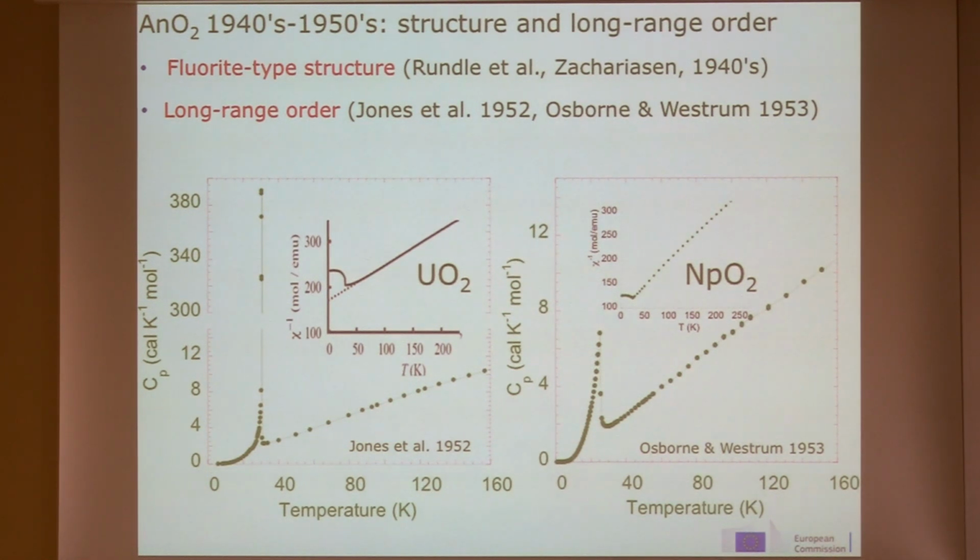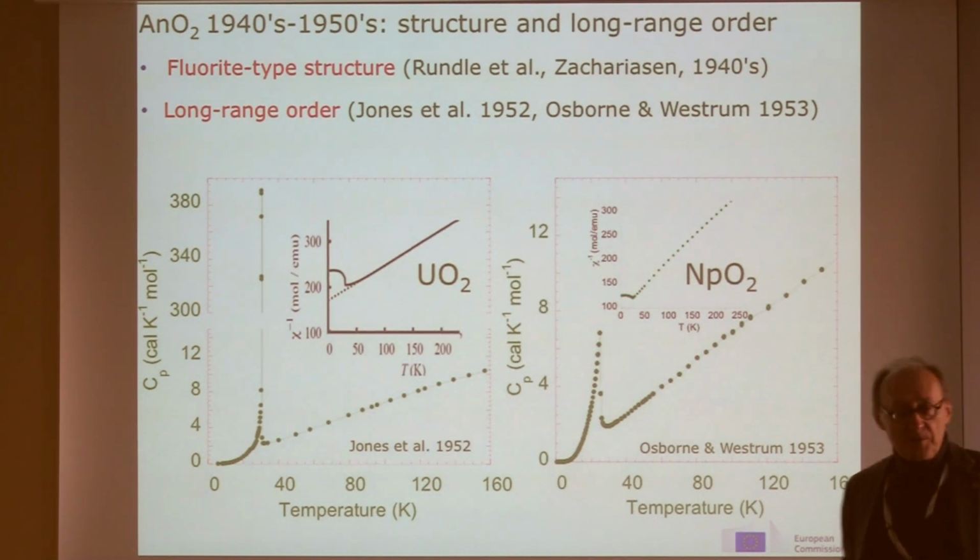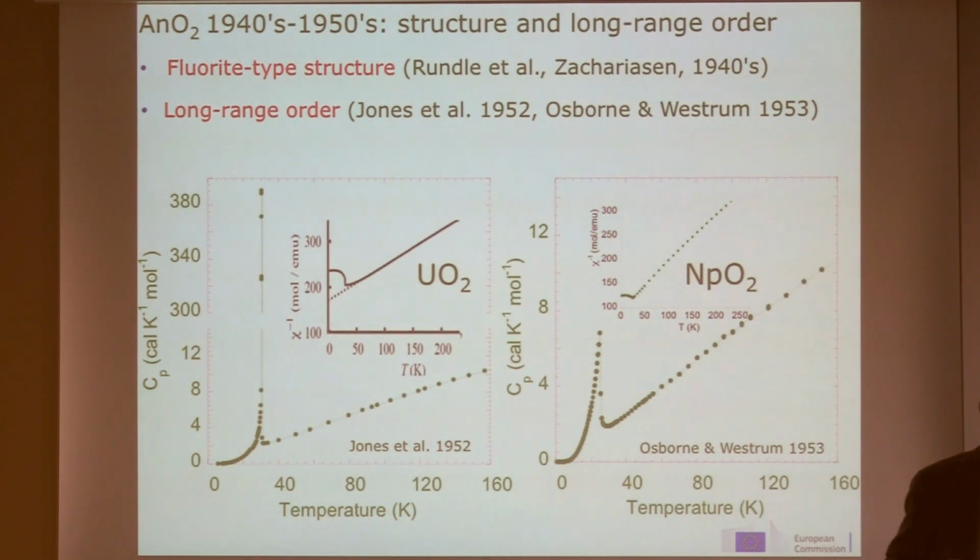From 53 to about 2010, a number of neutron diffraction studies, both on powder and on single crystals, and the Mossbauer spectroscopy experiment using neptunium-237, which is an active Mossbauer ion, failed to detect any magnetic dipole moment on the neptunium site. The upper limit set by the experimental sensitivity was about 10 millibohr magneton.